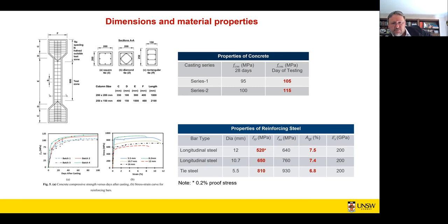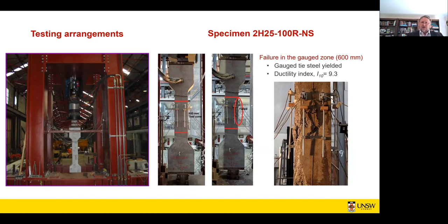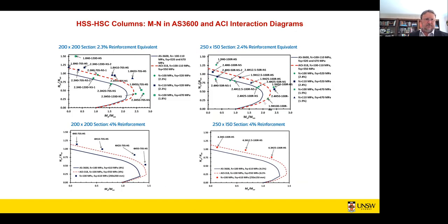So let's look at some of the results of this. So this is just showing the testing arrangements. You can see the loads applied at different eccentricities. We get the eccentricities approximately at setup, but we measure these strains both in the concrete through LVDTs, in the reinforcing steel through electronic strain gauges, and in that initial elastic period we can determine with high precision what the actual eccentricity is, so we correct for that. The one on the right here is actually a very ductile section. The I10 here, a value of 1 is something that's perfectly brittle, a value of 10 is something that's perfectly ductile, and this one here you see is very highly ductile. Anything over 5.6 is what we're looking at for AS3600.